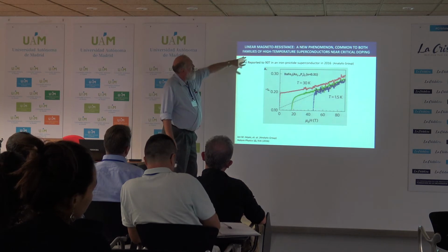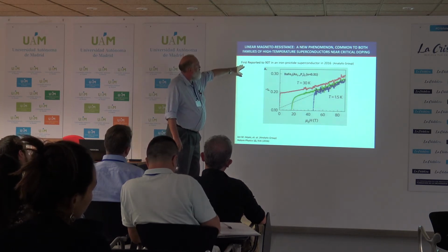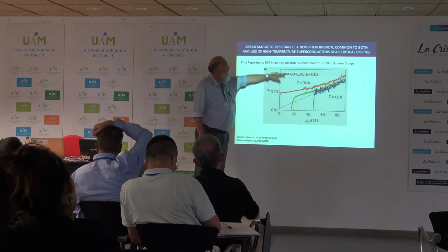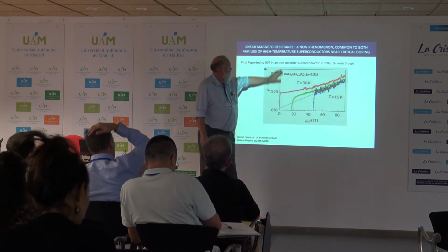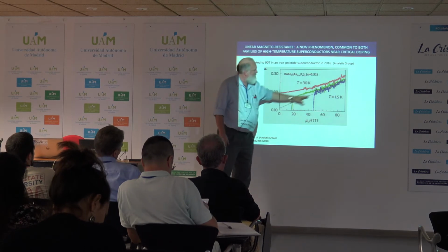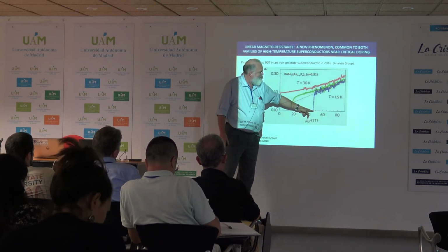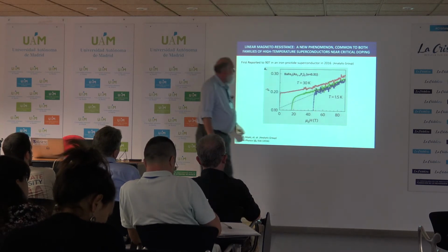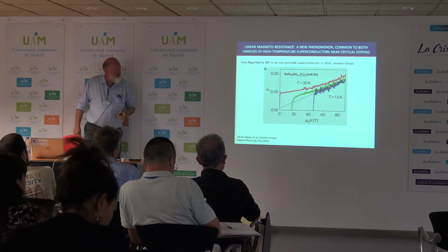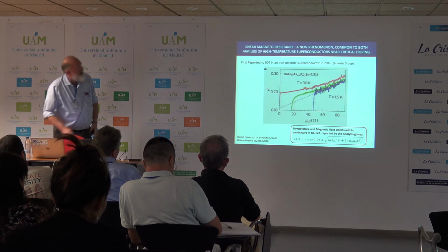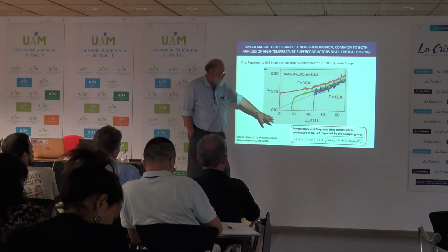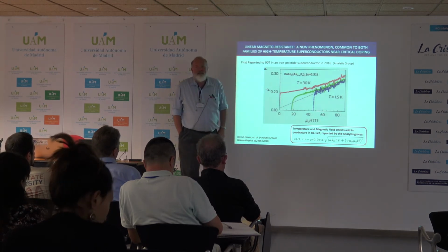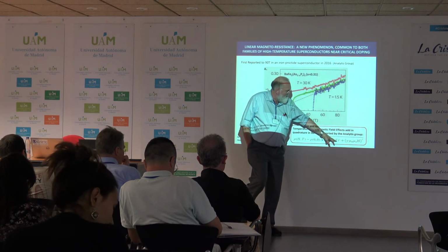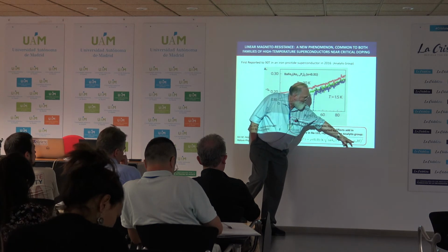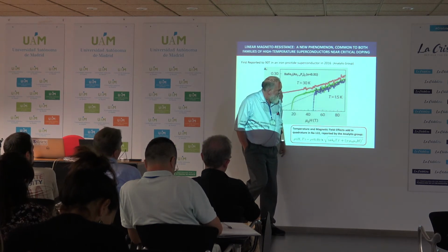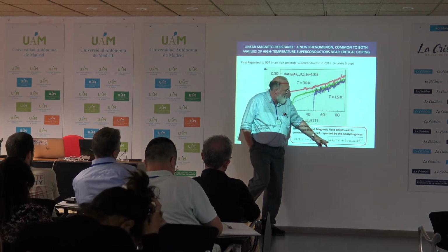It's a new phenomenon. I'll show that it exists in a second system, but it was first reported in data up to 90 Tesla in an iron pnictide superconductor, barium iron arsenic doped with phosphorus. This is the one pnictide that I show in this talk, and here you can see at low temperatures, once 47 Tesla has suppressed the superconductivity, you get a linear in H magnetoresistance for the remaining dynamic range of your measurement. And they find in this system, in barium 122, that temperature and magnetic field effects add in quadrature, which is a rather interesting result. So the natural scale to convert temperature to energy is kBT, and for magnetic field it's mu naught H, or mu B H, and then they have these two parameters they call alpha and gamma, but they add these two in quadrature.